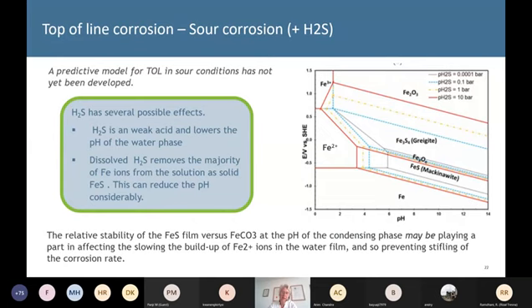We feel that the issue could be related to the pH effect and the fact that ions are removed so easily from solution by H2S. And we think that the relative stability of this product FeS compared to the iron carbonate means that you don't get that build-up of ions that you do in the pH conditions at the top of the line. So in sweet corrosion, you basically reduce the solubility of your iron over time, but that may not be happening in the sour system. Plenty of room for research for those of you who are in an academic field at the moment.